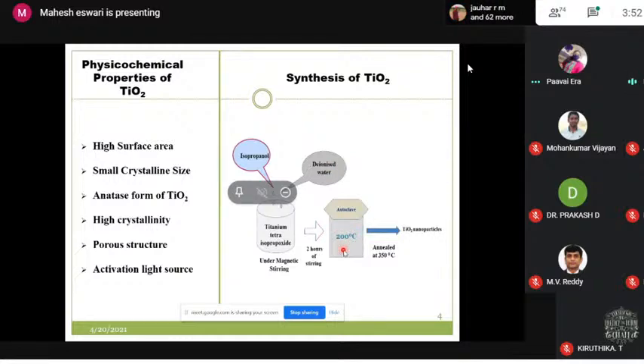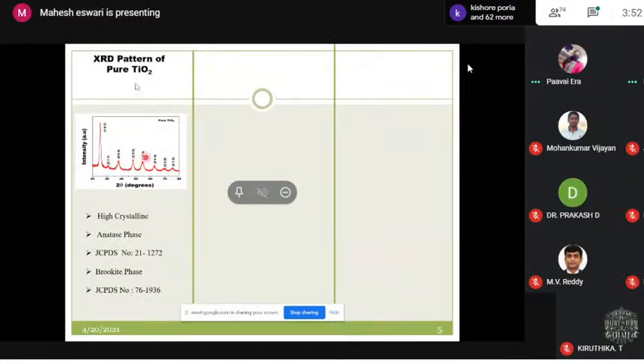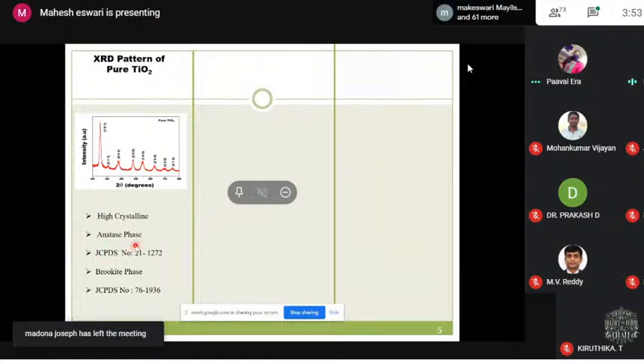Then it is centrifuged, dried in an oven, and then annealed at around 350 degrees centigrade, where we obtain titanium dioxide nanoparticles. Now, after obtaining the particles, we have to undergo characterization. So we have gone for the characterization of XRD. From the XRD analysis, we were able to see it is highly crystalline in nature, and the anatase phase of JCPDS file number 21-1272 exactly matches with this.